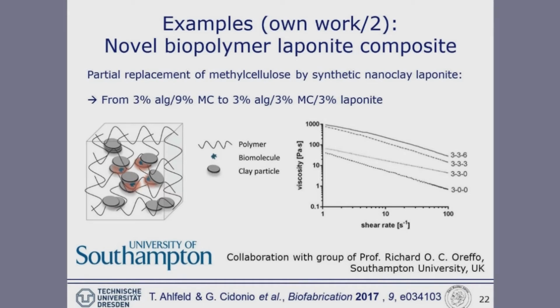So by adding distinct concentrations of laponite, we have been able to significantly enhance the viscosity compared again to the 3% alginate, and therefore making these composite blends much more suitable for printing and bioprinting. Also, this has been published recently in Biofabrication.